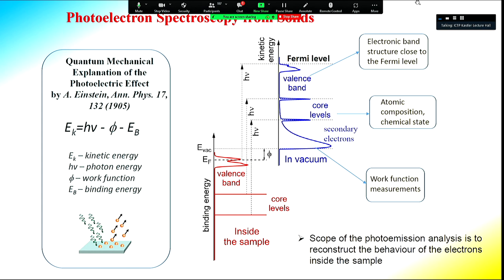There is also an exponentially growing background derived from inelastically scattered electrons, and information from this background can be used to determine the work function. The core levels are typically used to analyze the chemical and atomic composition of materials. An important part is also the electronic band structure close to the Fermi level, which is given by the valence band electrons. The main scope of photoemission analysis is to reconstruct the behavior of electrons inside the sample from its photoemission spectrum.